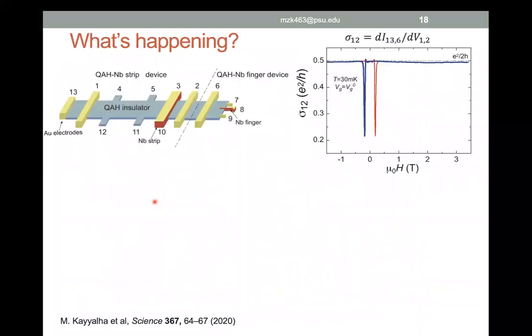So then what is going on? We have a superconductor, we have a strip, we put it on top of quantum anomalous Hall insulator. We always have quantized conductance if we have one strip. If we increase the number of strips to 2, then we see 1/3. If we increase it to 4, then the value of the quantized conductance just keeps dropping and dropping. And then we have also confirmed that the superconducting contacts, niobium in this case, provide relatively good contacts to the quantum anomalous Hall insulator. So there is no insulating barrier in between as far as we can tell. So what is going on?